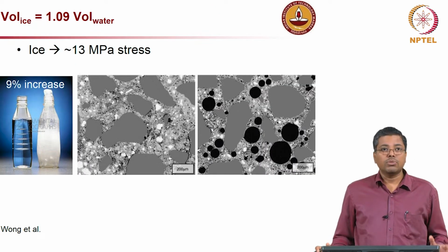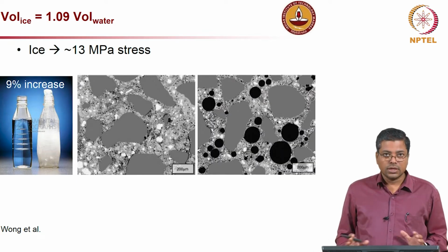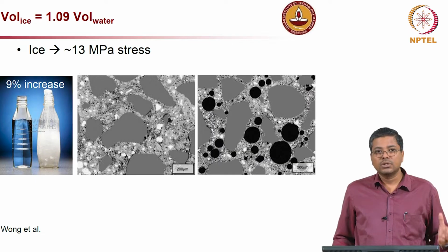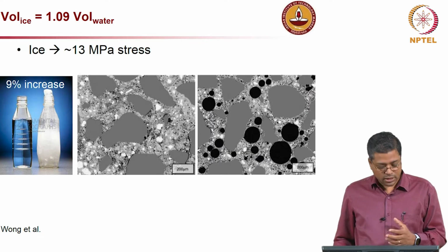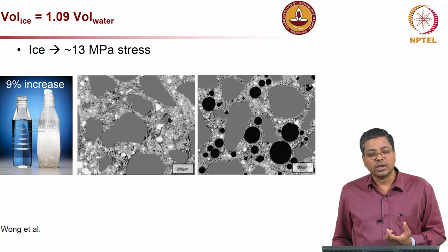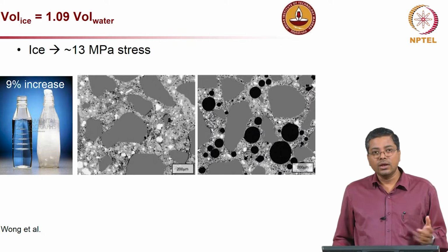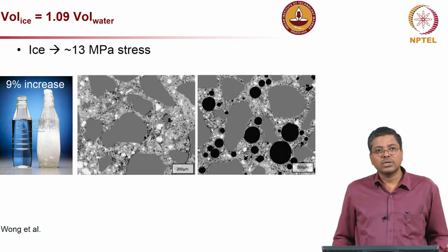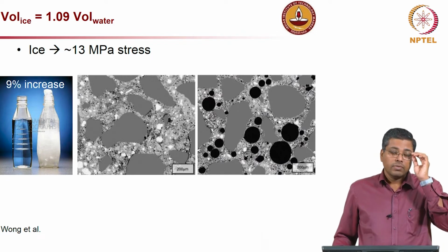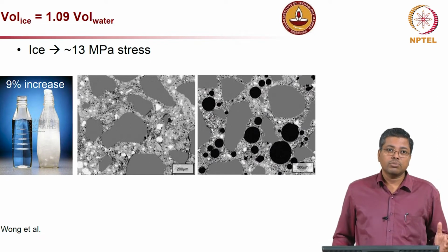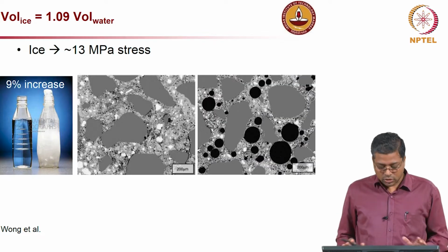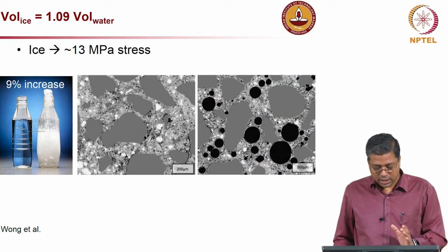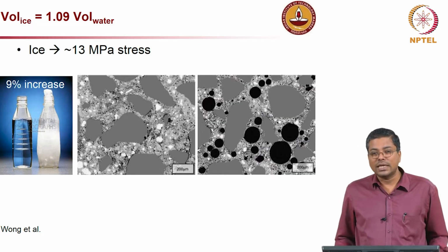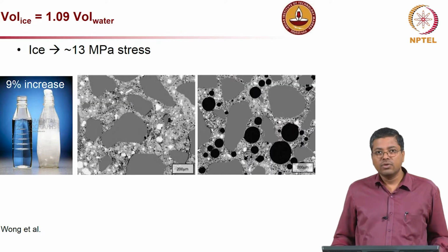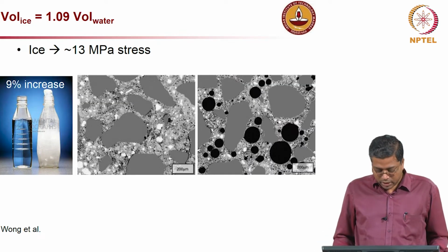Now, the first thing when we talk about cold weather or frost attack is ice formation in concrete. Where is the water used for mixing the concrete? If the temperature is very low, it will become ice, and as we know, ice formation means an increase in volume, about 9%, which leads to significant expansive stresses in the concrete. The first picture shows that 9% increase, and the second picture shows a system where there is not enough space inside the concrete, which will eventually lead to cracking because of this ice formation.